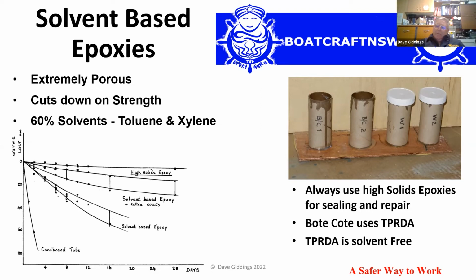they won't penetrate in. So the TPRDA added to the BoatCraft for any porous surface allows the epoxy to draw into the timber. It was mainly developed for densifying soft timbers like obeche and gaboon plywood and things like that, so that you can come up with a really dense surface but maintain its strength. And the other advantage is you're starting to put down a waterproof layer from the first coat.